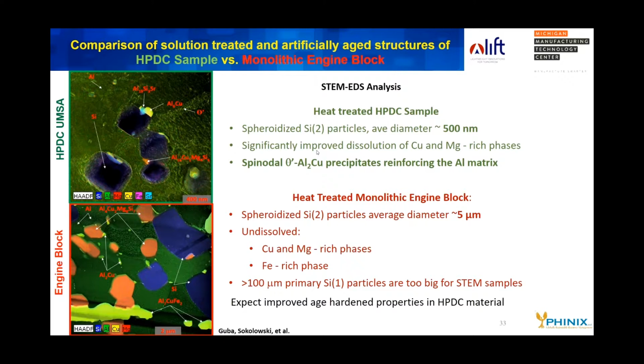So here are the pictures comparing the engine block and the UMSA solidified sample after artificial aging. You can see the silicon in purple, and the copper in blue, and theta prime nanoscale precipitates are barely visible in the aluminum matrix, but they are there, and they contribute to the hardness of the matrix after artificial aging.